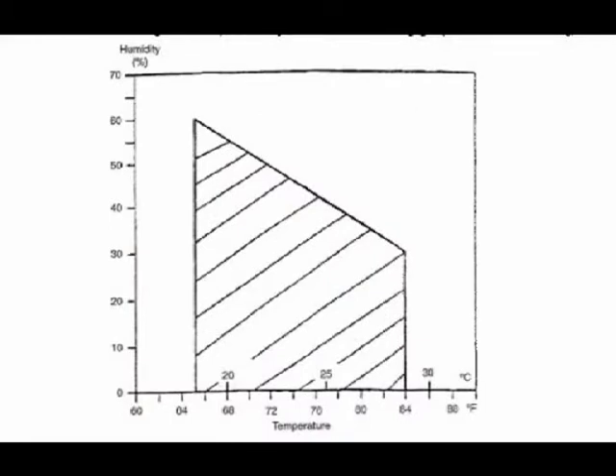First, assure that the layup room is humidity controlled, with humidity maintained below 60%. Here is a chart which has been used as a guideline when assessing humidity levels. Second, provide adequate time when drawing material from a freezer prior to use to bring the composite material to room temperature. This will eliminate moisture condensation on uncured material prior to cure.